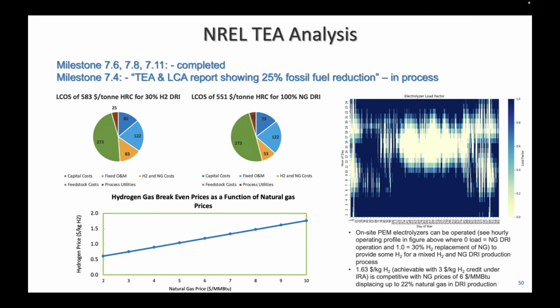1 ton of hot roll coil material, and the relative costs for utilization of hydrogen versus natural gas based on grid availability and electrolyzer load throughout the operating year of a typical weather cycle. And the bottom left actually shows what the cost of hydrogen has to be in parity with the cost of natural gas in these systems. And you can see that cost for hydrogen has to be pretty low, from under $1 per kilo to upwards to $1.8 per kilo if the natural gas price is actually high.